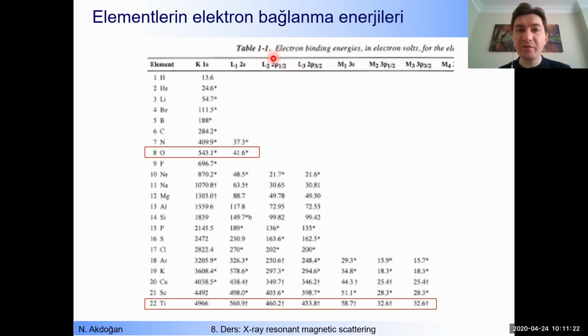Here we have a table of electron binding energies in electron volts. For example, for oxygen, the binding energy of the electrons for the K shell or 1s shell is 543.1 electron volts. If you are investigating titanium, we have binding energies like this, but of course, the energy range of each beamline is limited, okay? So usually, let's say, less than 1 kilo electron volt.